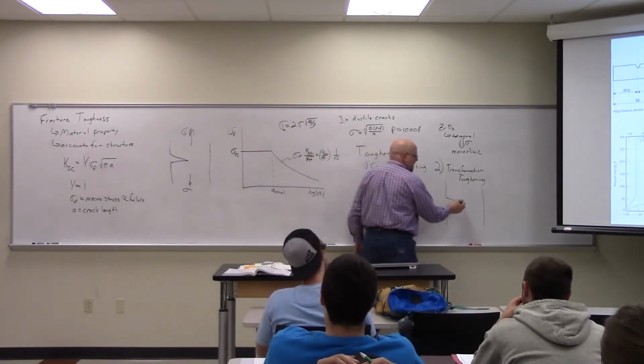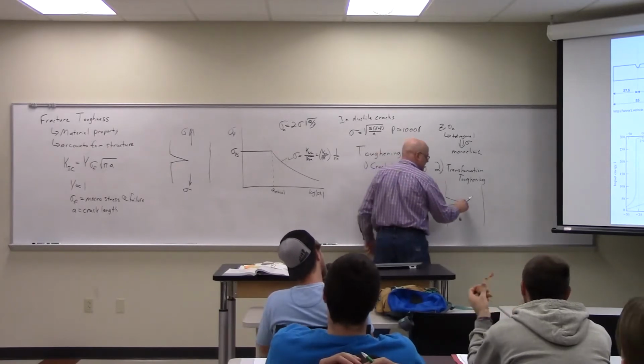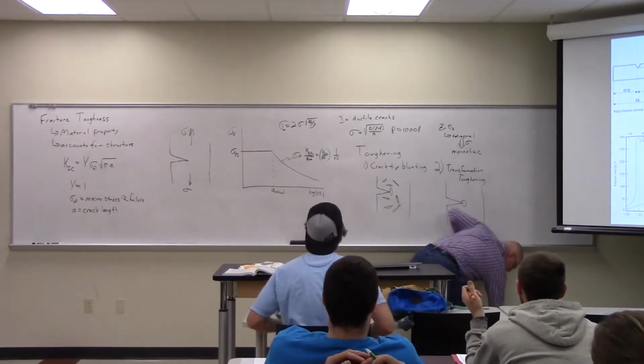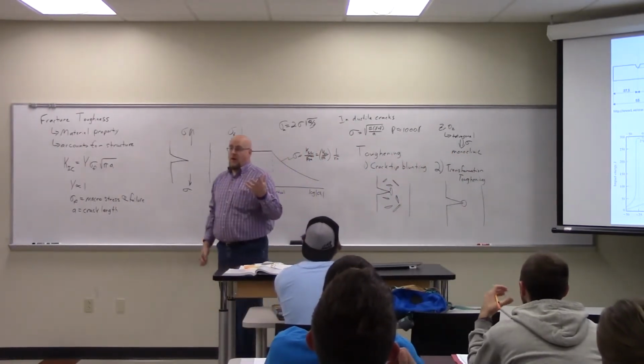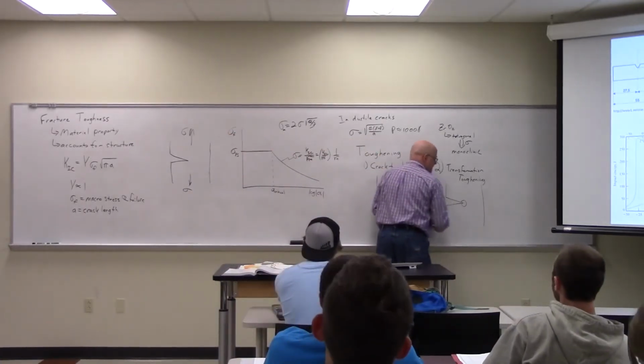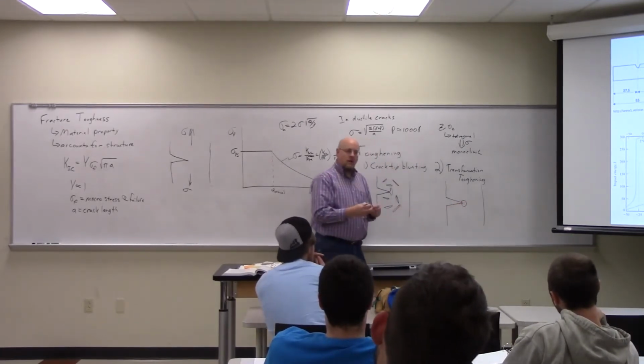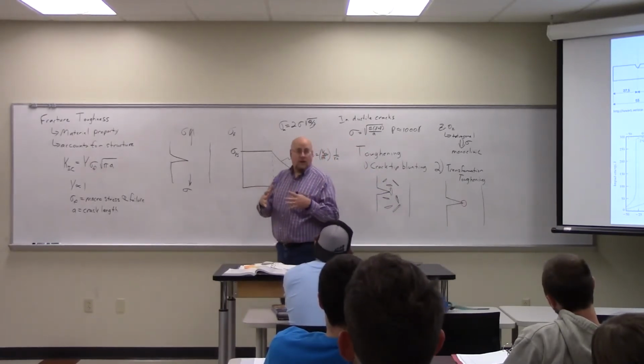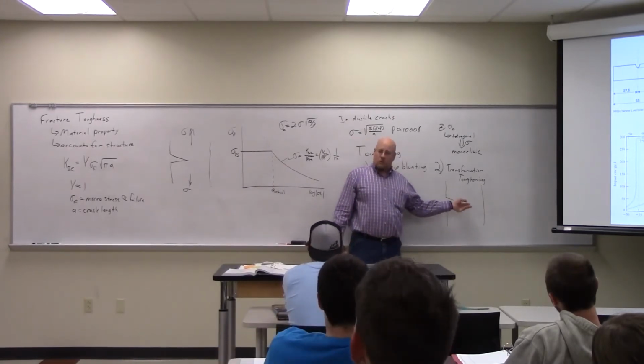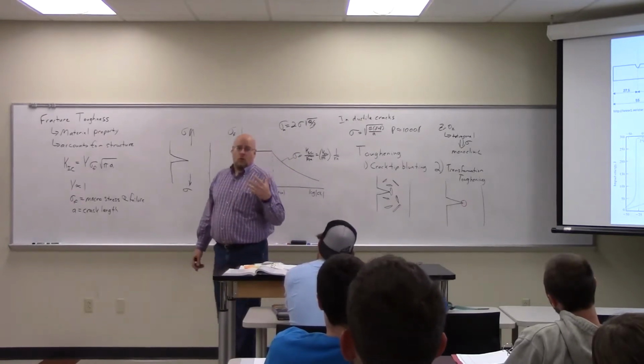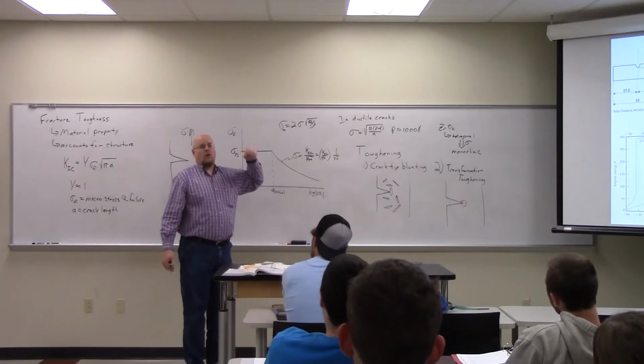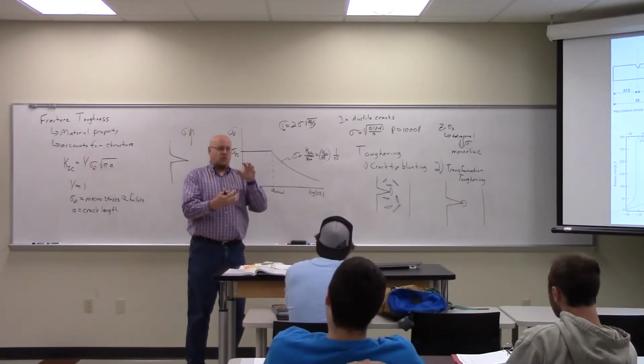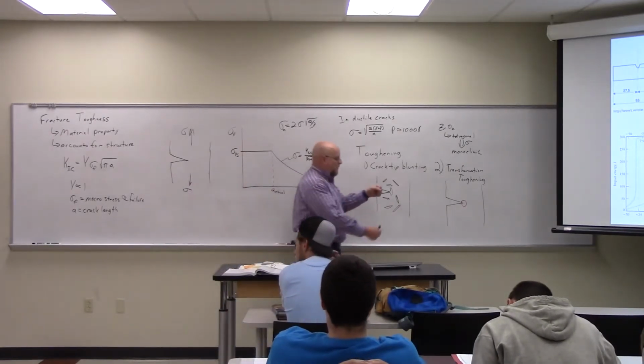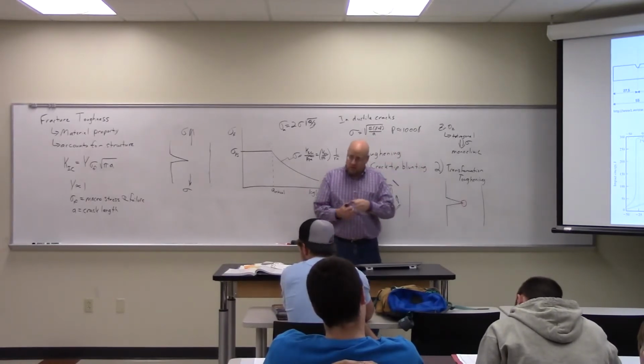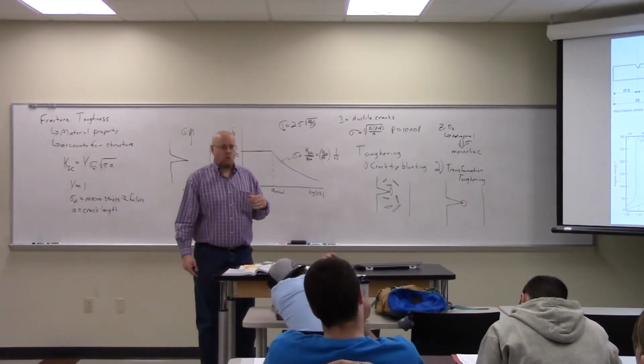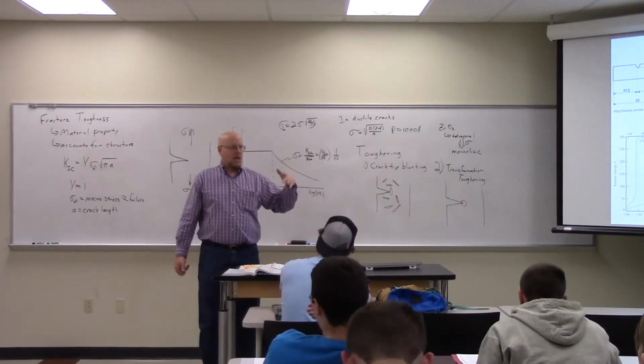Since it has a lower density, what happens is when it gets to that point, this region out here at the tip that experiences that stress suddenly decreases its density and therefore increases its volume. And the only way for that red region to increase its volume is for it to essentially close off the crack. It has to expand into the crack in order to increase its volume. So what it effectively does is it compresses the crack tip locally when it undergoes that transformation. So zirconium oxide, zirconia, is a transformation toughened material. As a crack begins to propagate in it, the stress created by this transformation stops it. Now, you can still get it to crack, but you have to apply the additional stress to now pull that monoclinic material apart. Okay. So it's tougher, but it's not infinitely tough. Does that make sense? Any questions?